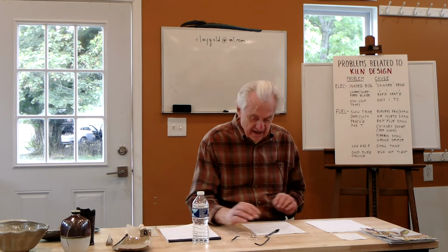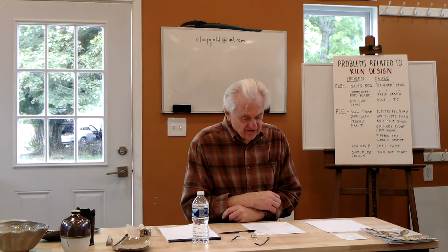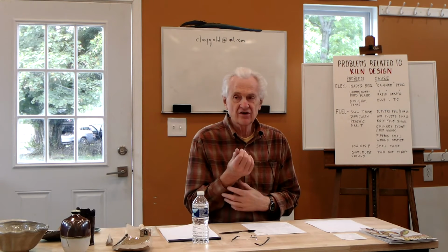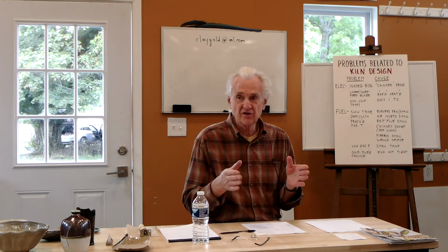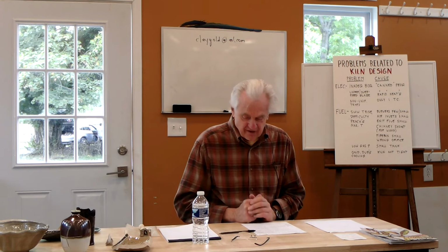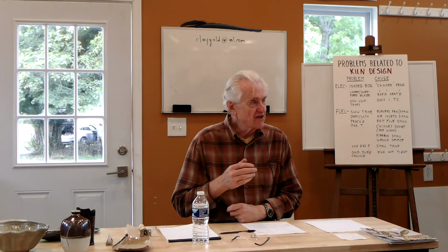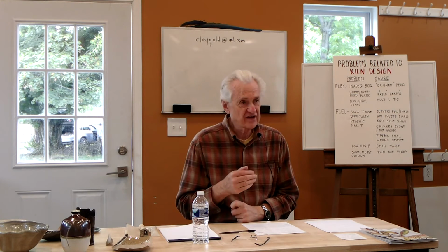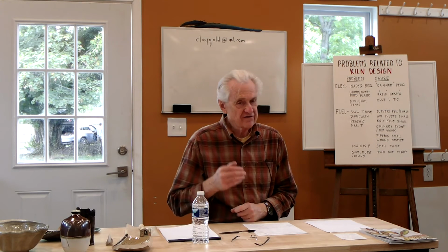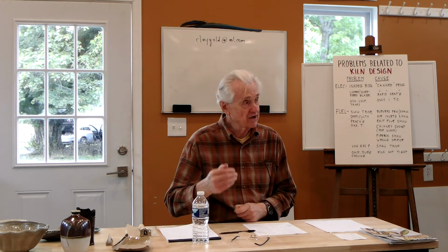Underfired or overfired glaze, and this again, the main reason I've seen, especially. Underfired would just mean that they might have a glaze where the standard program doesn't have all the features, maybe you need to hold, to adequately allow the glaze to mature. But especially overfiring, this is a fairly common thing with electric kilns. If you fire on a fast schedule with an electric kiln, when you're firing to a certain cone, the faster you fire, the higher the actual temperature is when you reach that cone.